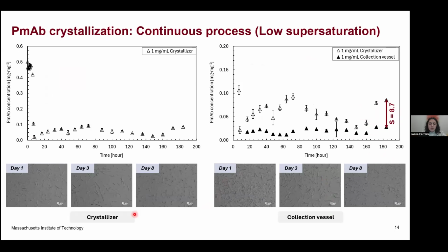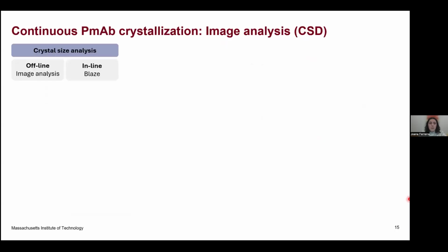But here it is very clear that from day 1 to day 3, we observe a clear increase in the crystal size, but then from day 3 to day 8, for both crystallizer and collection vessel, we see that the crystals are getting smaller, and this is probably due to secondary nucleation. It was not so for the other cases, it wasn't as clear as for this case.